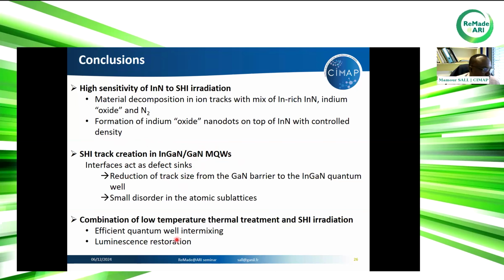And finally, we have demonstrated that by using a combination of low temperature annealing and swift ion radiation, we can have efficient quantum well intermixing. This is something we need for decreasing the polarization field at the interface. And we can also keep the luminescence in the green region.